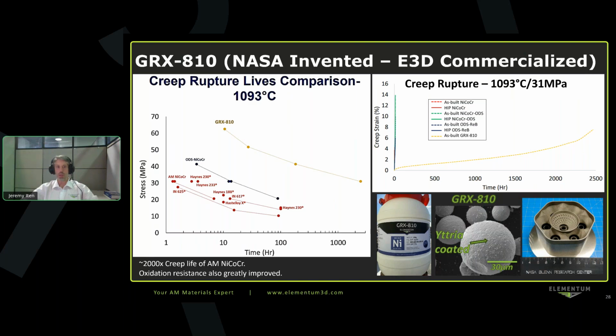So this leads to about 2,000 times creep life compared to AM nickel cobalt chrome alloy. The oxidation resistance is also greatly improved. So you can use this now at temperatures where you wouldn't traditionally use most nickel superalloys, like 1100 degrees Celsius and above, for example. You're still limited, of course, by the melting temperature of the alloy.